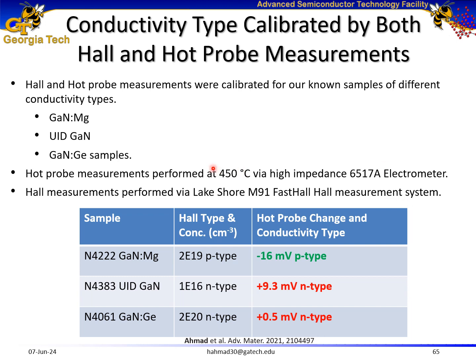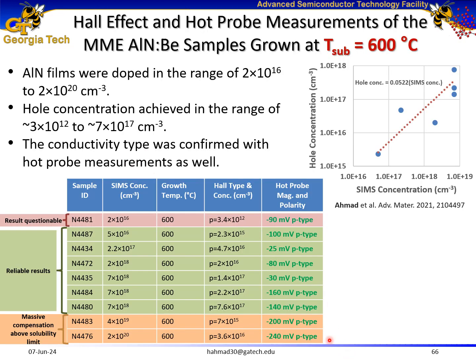But first, I calibrated Hall and hot probe measurements for our standard p-type, UID, and n-type gallium nitride samples. Later, I grew beryllium-doped aluminum nitride samples at a substrate temperature of 600 degrees C at different beryllium doping levels. Beryllium doping levels where the Hall results were questionable. Beryllium doping levels where we see massive compensation.